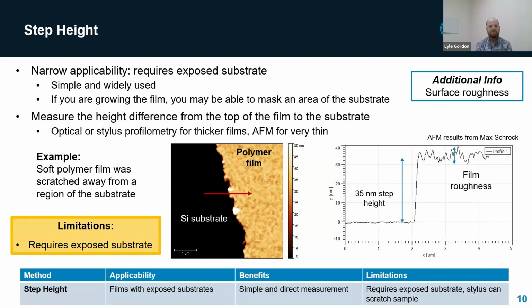But in many cases, if you're making the sample yourself, like you're sputtering a film, you can just mask an area of the substrate where it won't be coated and then remove that mask after to expose the substrate. In this case, this polymer film is soft and you can simply scratch it away easily without abrading the substrate, and then go ahead and, in this case, using an AFM, take the measurement, and looking at the step height of the film from the substrate, that basically gives you the thickness.